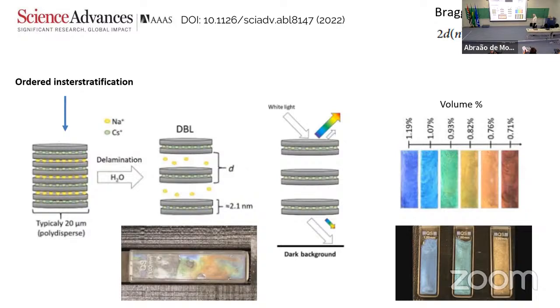So this thing that was shown down here shows that if you take these platelets, put them in water, mix a little bit, you get colors right away. It's a very rapid process to make these colors. And one thing that is important is that there's the dark background. Because most of the light you shine through this system goes through, most of the white light goes through. So you need something underneath here to absorb the white light. And if you have a white background here, the light comes back and you see no color.